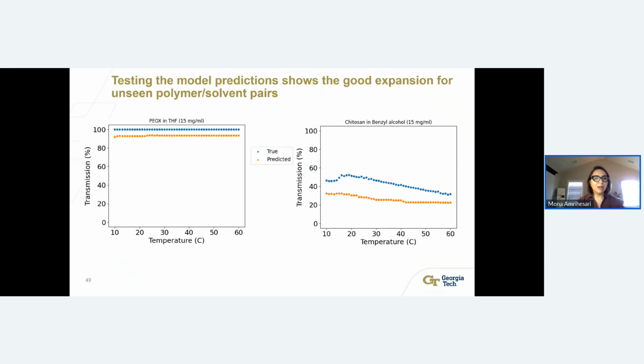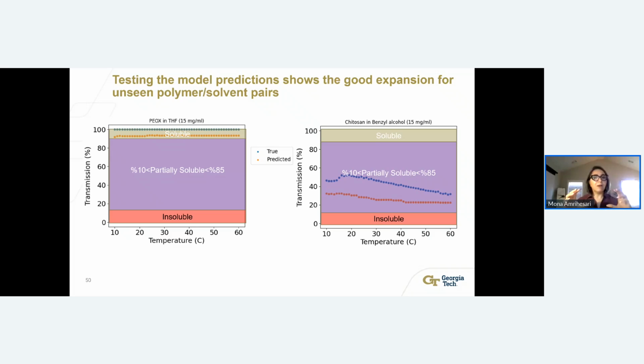But if you look at testing this model prediction for the unseen classes, these are two examples, and we validated further with experimentation. The true value, the blue one that we validated through experimentation for this polymer in THF at 15 milligram per milliliter, is 100%, and the predicted value is 90%. So it shows that it's not 100% accurate. As you remember, we had the 6% RMSE, but it still shows the same trend and value, as for the examples on the other polymer. And it's within the region of what we expected, or what we classified at the start.